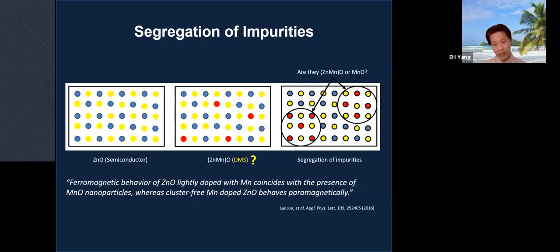For example, this APL paper published in 2016 shows manganese doping of zinc oxide. This is a quote on the bottom here from the paper: ferromagnetic behavior of zinc oxide lightly doped with manganese coincides with the presence of manganese oxide nanoparticles, whereas cluster-free manganese-doped zinc oxide behaves paramagnetically. So this suggests there may be a segregation issue, there may be non-uniform doping here and there.